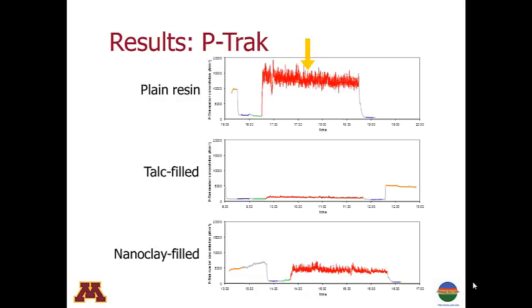The plain resin plaques exhibit the highest particle concentrations among the three types of plastic during the shredding period, averaging on the order of 15,000 particles per cubic centimeter. Although concentrations bounce up and down over short intervals, the average was steady throughout the shredding period. The concentrations measured when the conventional talc-filled resin plaques were shredded were much lower, just above background concentrations and considerably lower than room concentrations. The number concentrations when the nanocomposite plaques were shredded were approximately 5,000 particles per cubic centimeter, higher than the talc-filled resin plaques, but lower than the plain resin plaques.